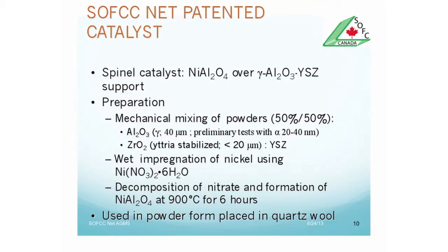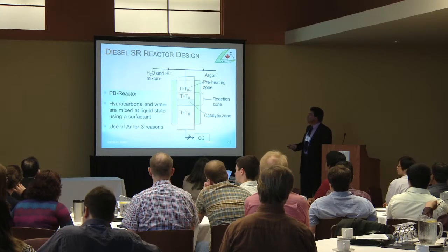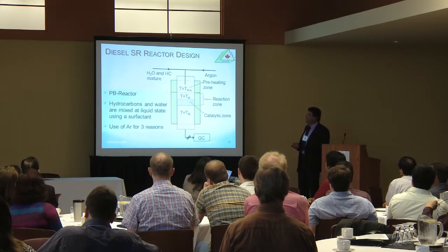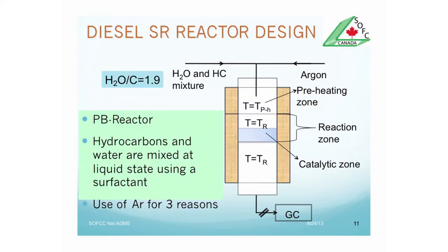The production was made easily and conventionally through wet impregnation. Decomposition of nitrates and formation of the spinel phase for 6 hours at 900 degrees, and it has been used in powder form in quartz wool. This is the configuration of the reactor. It's a packed bed, very simple.